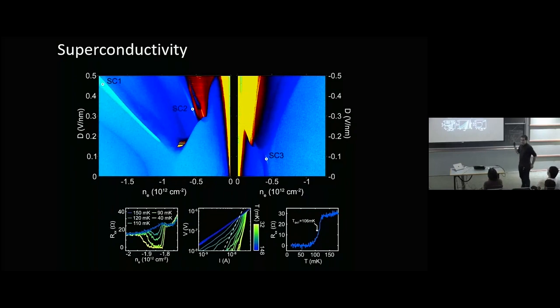It's not the last time in this talk that I'll tell you about being surprised, because we thought we were being careful scientists doing a control experiment that was going to crack everything open, and then you find that your control experiment is more interesting than the experiment you were trying to do. So indeed, this is the same phase diagram, right? I showed you in compressibility all of these different phases, but it turns out that at the boundaries of many of these phases, there are superconducting states. So I call them superconductor 1, 2, and 3 here. I'll get back to these later.